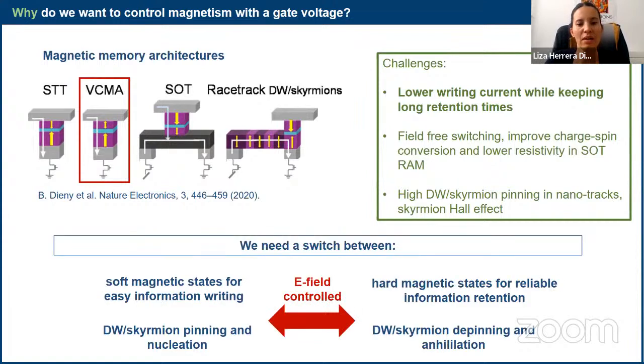So this is really where voltage control of anisotropy could be a game changer, because with the same material, with the same device, having a local gate, we could go from a state which is easy to switch with a low anisotropy, and then once the switching is done, switch it back to a hard magnetic state, which is very robust against thermal fluctuations for storage. So this is why we want to control magnetism with a voltage. And this also extends to domain wall and skyrmion dynamics that we can control by defining pinning sites or pinning potentials with a voltage.